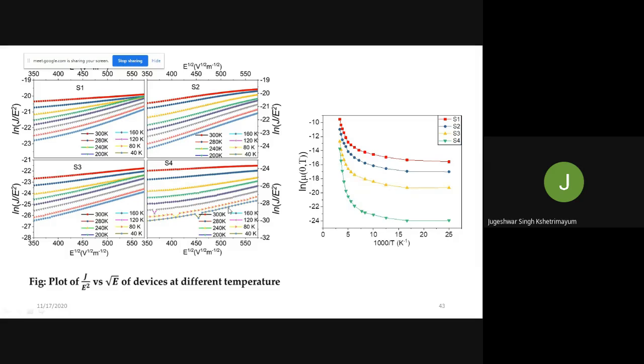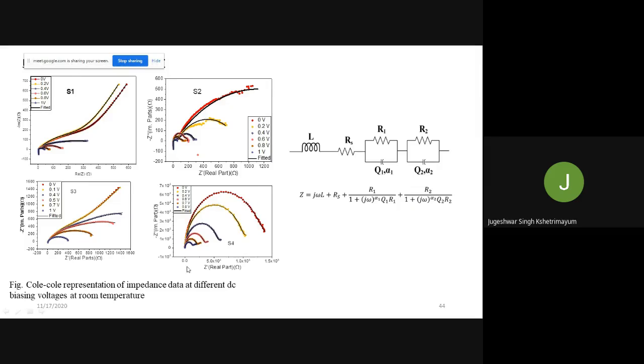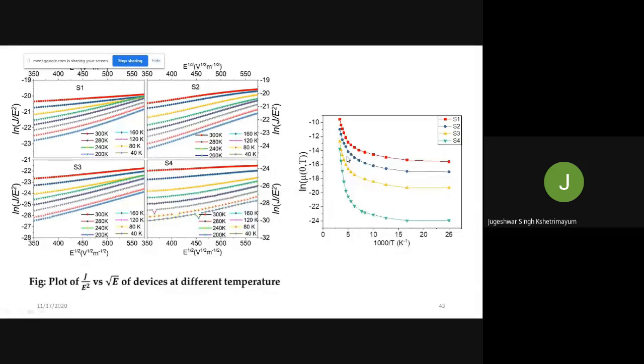That model we call the Poole-Frenkel law, where J is proportional to root E. Mobility mu is equal to mu naught e to the power some factor into root E. So now the factor root E comes into the picture. This is the root E dependence here. So in this one also we can say very interesting results: the field dependence is very clear, and the mobility is much more dependent on the field at the higher temperature side compared to the lower temperature side.